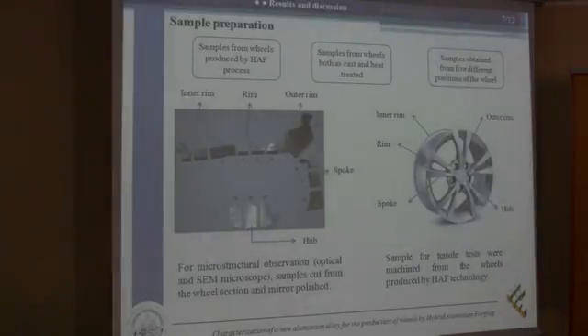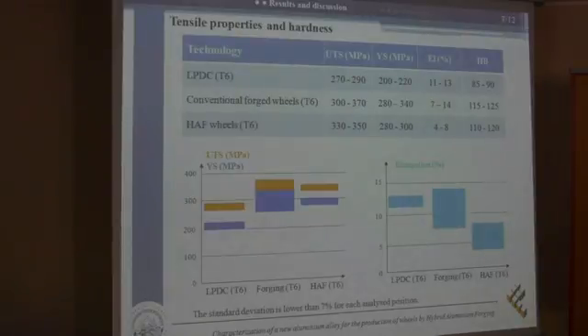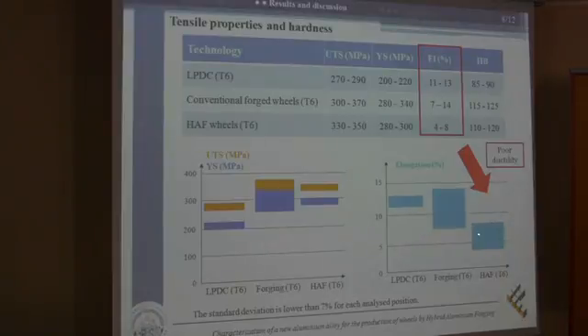Then for further characterization, samples were taken from wheels actually produced by this innovative technique, both from as-cast wheels and heat-treated wheels, and samples were taken from different parts along the wheel section. The tensile properties show, as it is possible to see from this plot, that ultimate tensile strength and yield strength are really improved compared to the performances of cast wheels, and the values are really similar to those of forged wheels. On the other hand, the elongation is the critical parameter, because the elongation values were less than the performances of both cast and forged wheels.